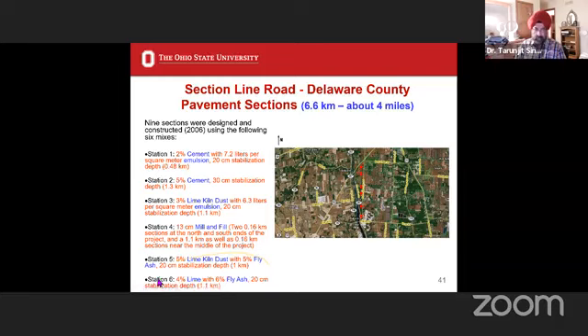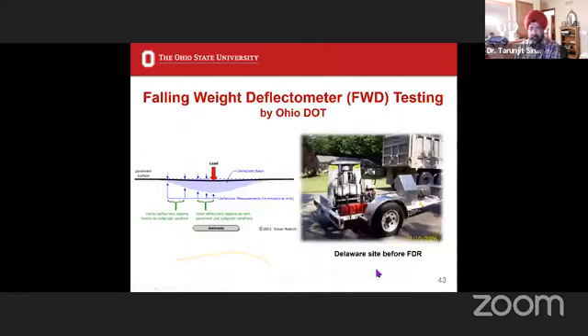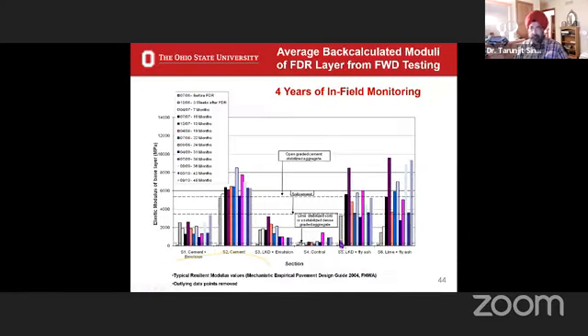We believe that this station six mix is a superior mix and has more pozzolanic materials than station 5. Now, if I look at both of these in this figure, in terms of strength development, what is happening is that the LKD and fly ash, to begin with, this gray bar at 3 weeks, gives you much higher